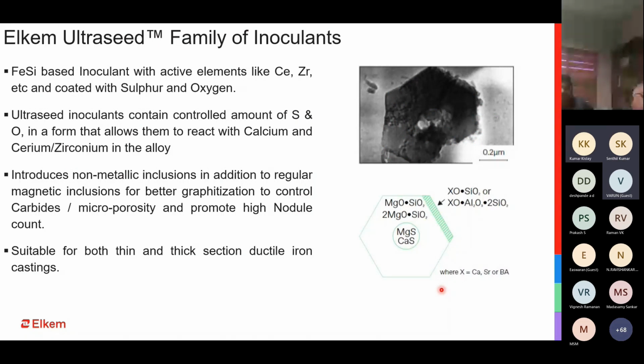And finally, I have been talking about it since the beginning, the UltraSeed family, that is the sulfur and oxygen coated inoculants. So a ferrosilicon based inoculant, like I have mentioned, does have active elements. But when these active elements are coated with sulfur and oxygen, it allows them to form their own inherent inclusions, which give you a much better graphitization and a much better control on the carbides and microporosity. This type of inoculant, I will not speak again about it because I've already done so, is more suitable for both thin and thick section ductile iron casting, and definitely finds its application more in ductile iron casting compared to gray iron casting.